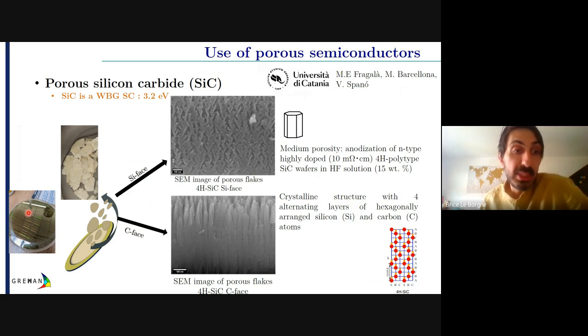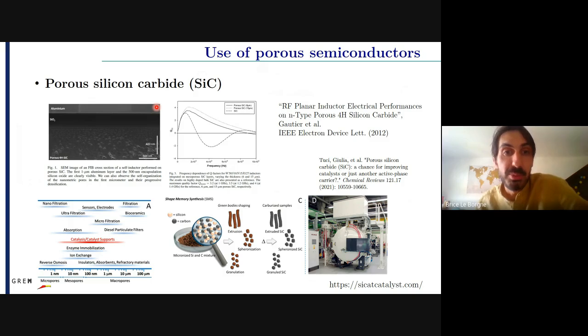With silicon carbide, you can also etch it by electrochemical etching and obtain different shapes depending on if you etch the silicon face or the carbon face. And it's very interesting to try to use this semiconductor, because it's a wide bandgap semiconductor, so 3.2 eV, and it can probably offer, of course, you already understand maybe where I'm going. You can use it for optical properties. And it's not so common to use porous silicon carbide within devices. So of course now it's really developed for power electronics, but not porous silicon carbide, only silicon carbide. So I think there's space also for that in the industry, even though we need to improve it a lot.